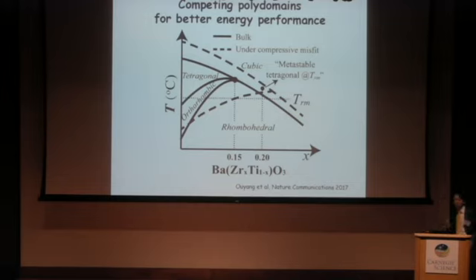In order to create such a polydomain structure, I started from scratch with barium titanate. We know barium titanate in the undoped state is a very stable tetragonal. I tried to make a polydomain film out of only a single phase, only barium titanate, but I always got the polydomain of tetragonal. It proved to be not much use for dielectric capacitor applications because 90-degree domains are very difficult to switch, as you all well know. So I tried to make it rhombohedral, to allow the polarization to have a certain angle with the applied field. In this case, I doped it with a little bit of zirconium, which is larger than titanium.